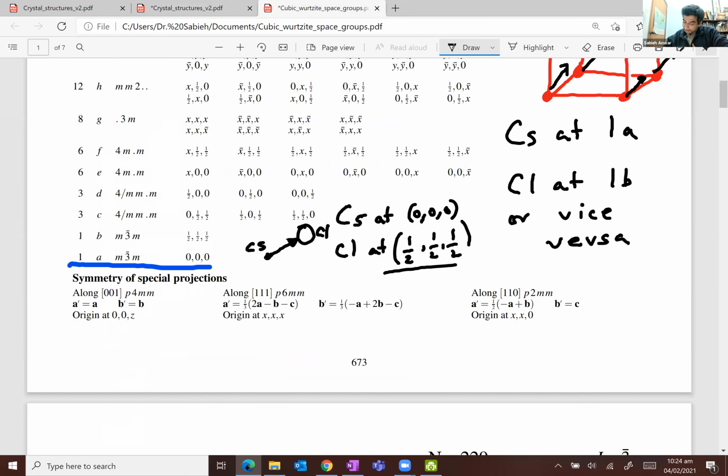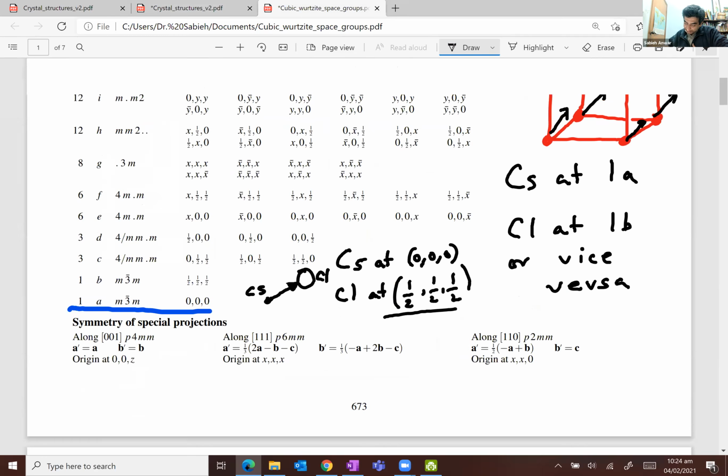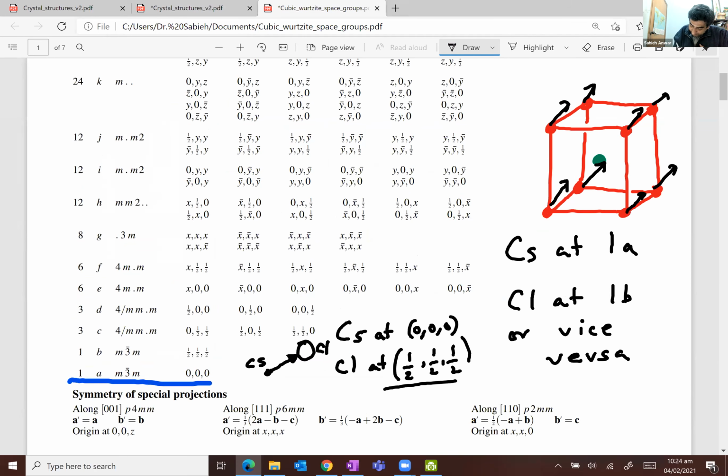So what we could do is, now let's look at Pm3̄m again. So there's a barium atom here. There is a titanium atom here, and then we need oxygen atoms. So the oxygen atoms are at the position 3c. And there are three of them. So there's one barium, one titanium, and three oxygen atoms.